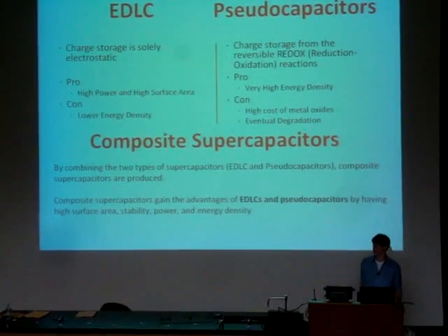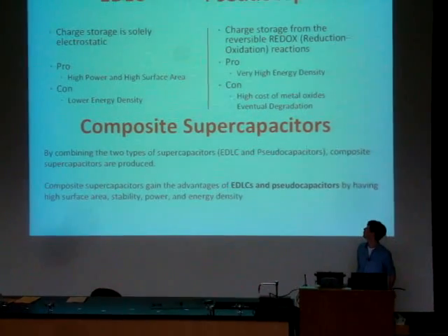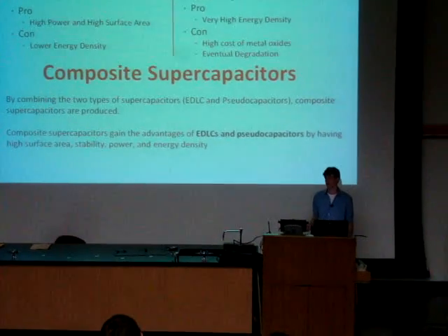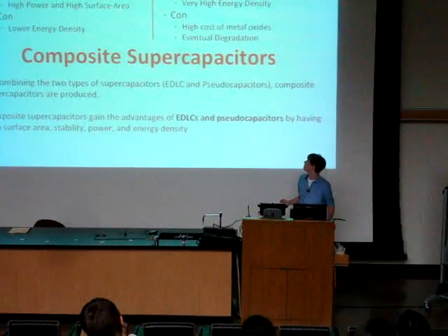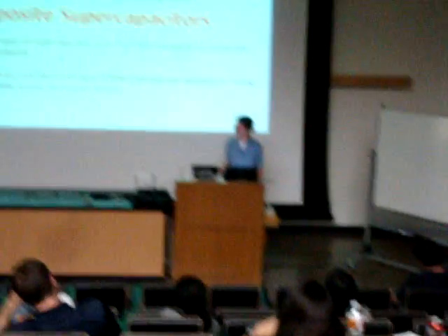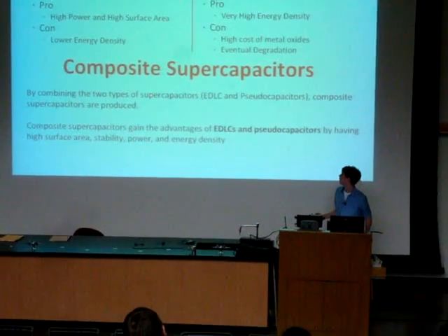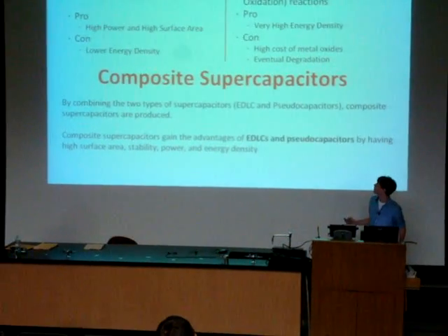However, there are also pseudocapacitors, which work by having reversible redox reactions along the surface of the electrode. They have very high energy density because of the chemical reactions occurring. However, the high cost of metal oxides and the eventual degradation from continuous cycling of the electrodes ends up causing them to degrade. Now, we worked with composite supercapacitors, which are a combination of both.